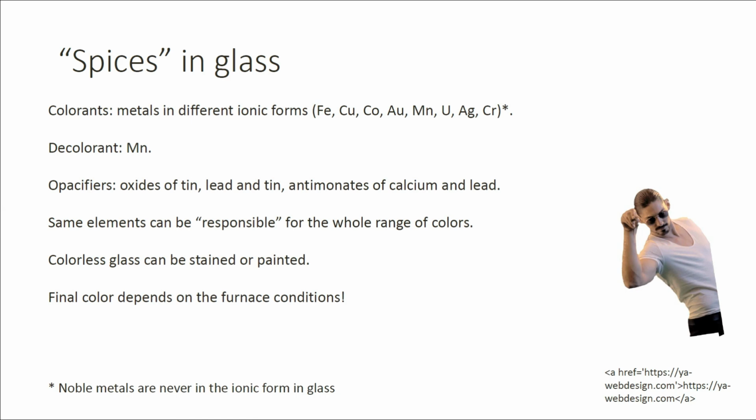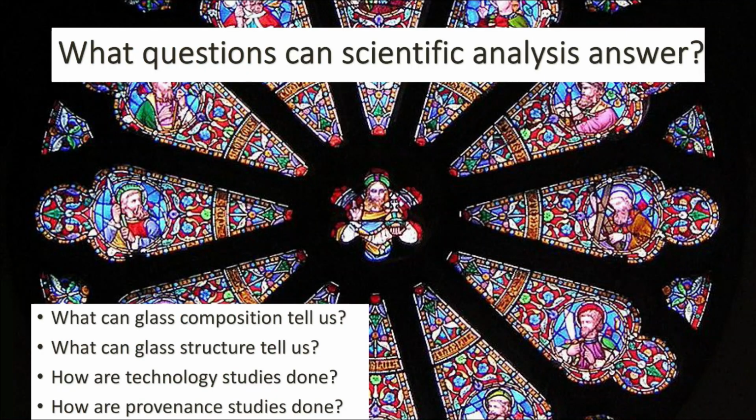Coloring of glasses was usually done by addition of transition metals that colored the bulk of the glass. Staining is coloring of the thin layer of the glass surface. Opacification is making the glass opaque, usually with the addition of crystals. And finally, painting is just applying a layer of paint on top of glass surface. It doesn't entail any chemical interactions.